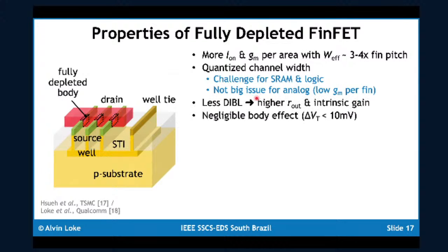We talked about less DIBL for higher R out and better intrinsic gain as a result. The body effect is essentially negligible, with typically less than 10 millivolts of VT shift across a supply voltage change in body-to-source biasing. The mismatch is substantially less in such a device because in a fully depleted device, in principle, you're not sensitive to random dopant fluctuation.